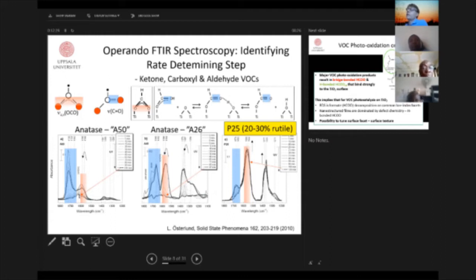And here you can see with operando FTIR spectroscopy how they build up on the surfaces in the course of reaction. Whenever you have a crystal structure, for example rutile or other common structures, you build up these kinds of species which inevitably eventually poison the catalyst. But on the left-hand side, you can see that you can actually do better. It is possible to expose crystal structures which do a better job.